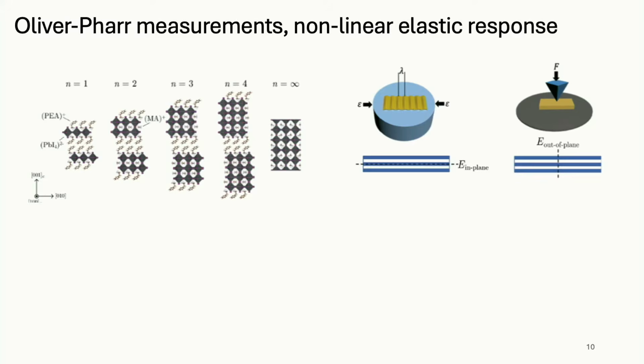Then we go back, there's 2 layers, and then the spacer, and then 2 layers, then 3, 4. And then n equals infinity will mean we never get to the molecular spacer. This is back to the 3D hybrid perovskite. We would say that's the n equals infinity member of this series. One thing to note is, do you see the part where it's like the perovskite layers? The small molecular cations are embedded here, except for n equals 1, where there are no pockets. You get this small molecular cation as soon as you get to n equals 2. That'll crop up later.